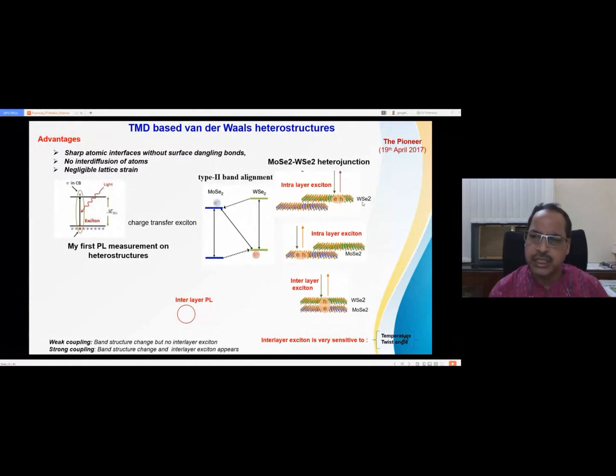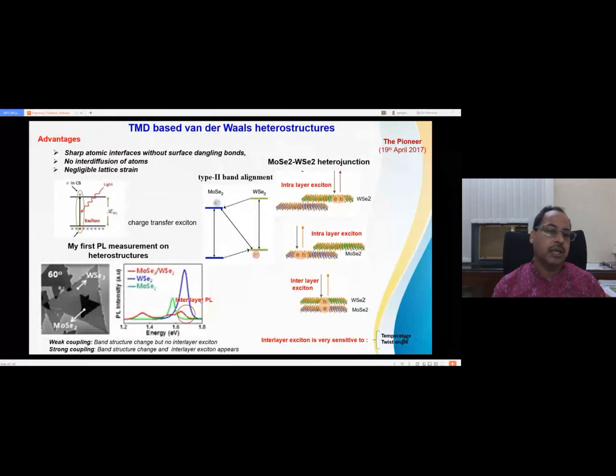So in case of a monolayer, you can see there is an intralayer exciton. Here electron and hole belong to the same layer. Similarly for MoSe2. But when you talk about the heterostructure, electron and hole belong to different layers. This is called an interlayer exciton. So we did this on our sample. This is the first observation of it. Initially, there was a theoretical calculation that it will show the interlayer exciton. This is our first experimental demonstration of the interlayer exciton.